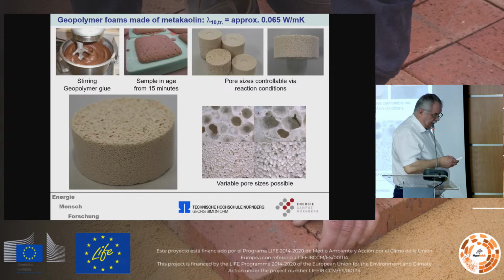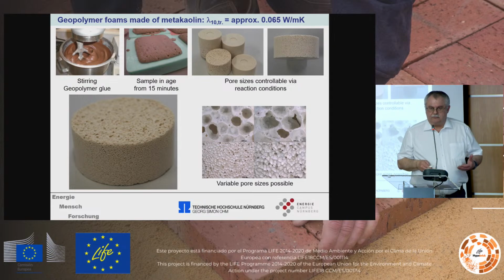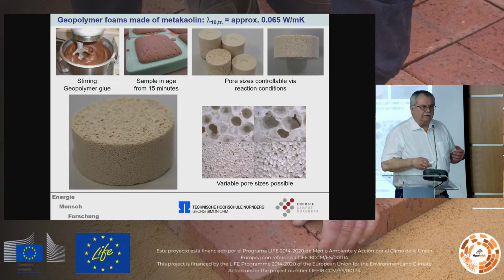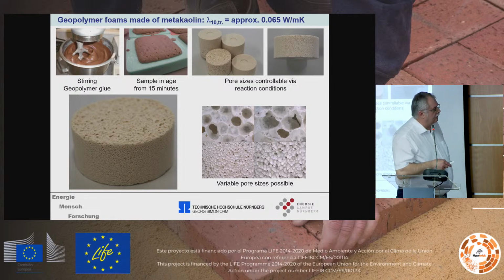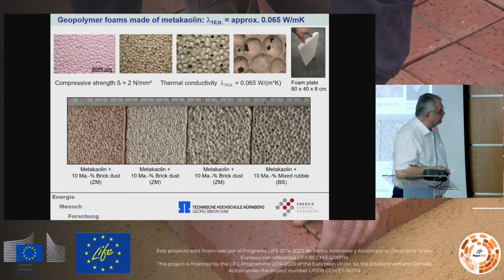We create a foam. Here you see the glue, the geopolymer glue, and we prepare it, and we put in this material H2O2 or aluminum powder, and so we can create hydrogen, and the geopolymer glue in 15 minutes grows up, and you can have a foam with pores in different shapes. Here you see the geopolymer foam in different shapes. And you have here, with the foam, the compressive strength about 2 megapascal and the thermal conductivity about 0.065 watt per meter and Kelvin. Here, structures of the pores.